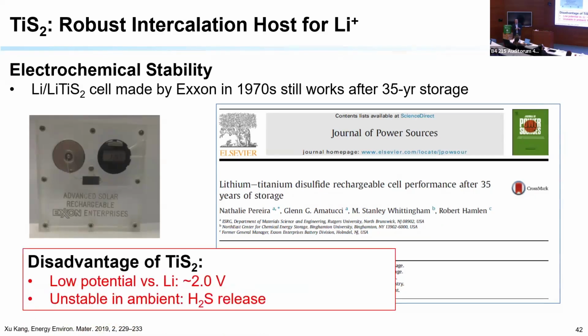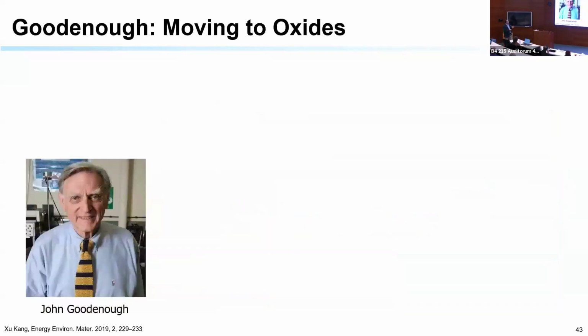But the titanium disulfide had two disadvantages. Number one, it actually only works at 2 volts. So compared to the lithium, that means the voltage window of the battery is only 2 volts. This is considered low. Today's lithium-ion battery is around 3.7. Remember, more voltage means more capacity, means more energy density. And also, it's unstable in ambient. It can release H2S, which you know is a nasty gas. So people started to look for different materials.